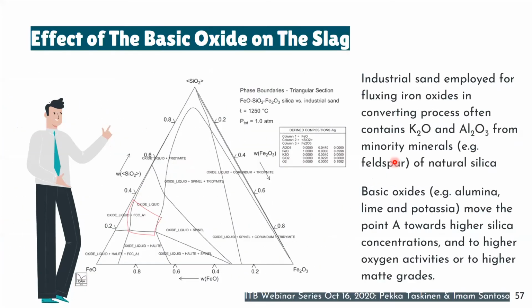However, in some concentrate, like in Indonesia, the concentrate can contain alumina and also potassium, and this will also affect the stability of oxide. For example, we can see here that when the potassium or alumina exists in the slag, it can enlarge the liquid slag area.